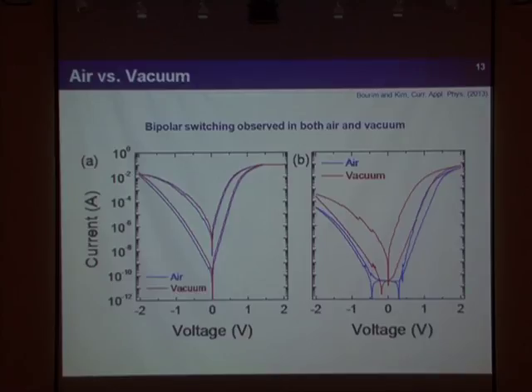I should note that sometimes the switching behavior doesn't change much between air and vacuum, but sometimes we see a quite big change. You can see the main difference of these two samples: the left one's current level is much higher than the right one.